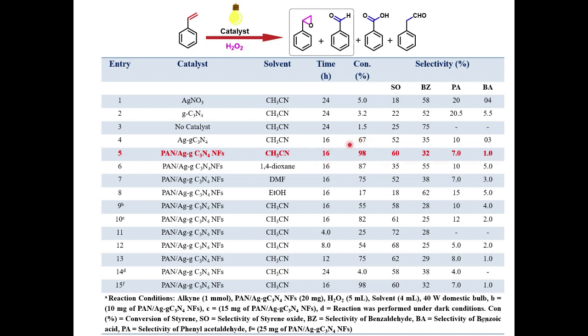In this 98% conversion, styrene oxide forms 60%, benzaldehyde 32%, phenylacetaldehyde 7%, while benzoic acid is only 1%. Means the major one is styrene oxide. And when we compare this particular nanofiber in different solvent conditions, the percent yield is reduced, and even in the selectivity studies, styrene oxide formation is very less. Here the benzaldehyde is very high, but it is selective for the styrene oxide.